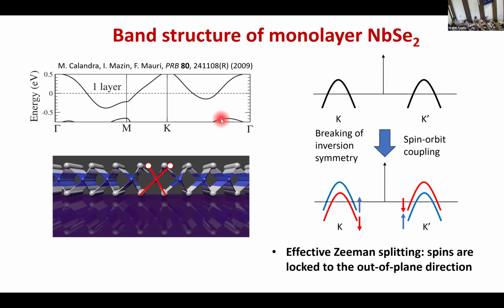So it lacks inversion symmetry. Due to this breaking of inversion symmetry in this monolayer, the spin orbit coupling effect for the K and K prime points are opposite. The strength is the same, but the direction is the opposite. So people argue that due to this spin orbit coupling effect, for the spin splitting around the K point, let's say that the spin down is moving down and the spin up is moving up, then the opposite happens for K prime points. And now, after considering the spin orbit coupling, the pairing happens between K and K prime points. But the spins here, for example, the blue band pairs with this red band. The spins are now locked because you already have a spin splitting due to this spin orbit coupling effect. And the direction of these spins are pointing in real space out of plane.